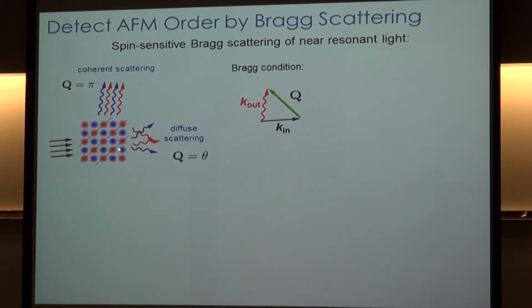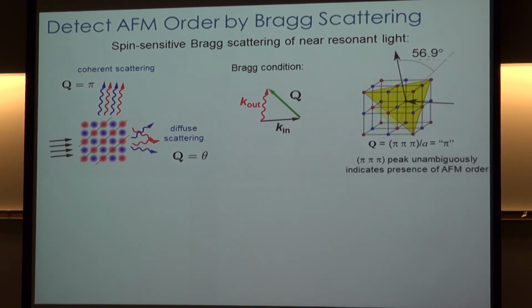You'll see these diagonal lines here. It may be a bit faint, but those diagonal lines are at this 45-degree angle. They correspond to what we call the (pi, pi) direction in terms of the reciprocal lattice vector. At that particular angle, which we call pi, you get coherent enhancement of the scattered light. If you have a detector over there, and it satisfies this Bragg condition, that the wave vector in and the wave vector out along this direction differ by a reciprocal lattice vector q, then you get this coherent enhancement.